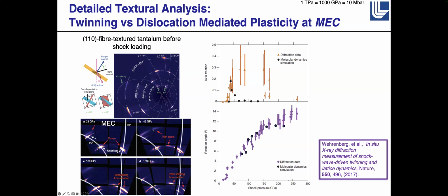And so you can see new peaks out here that are different from just compression, and you can see kind of a peak splitting due to the rotation of the lattice. And this shows basically the twin fraction on top and the rotation angle underneath as a function of pressure, which was kind of neat for how dislocations and twinning mediate the plasticity.